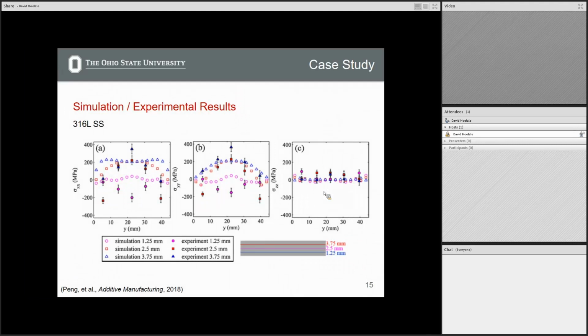Okay. Residual stress measurements. This is where maybe our experiments in our model was, I would say, qualitatively the same, but had a decent amount of quantitative difference. This is simulation, so the open symbols are simulation, then the filled ones are actual measurements that we took off this neutron diffraction machine. So main message here is that you get stress profiles that somewhat qualitatively match what you would expect here. So the blues essentially match the blues, the reds somewhat match the reds, and then the pinks somewhat match the pinks here.